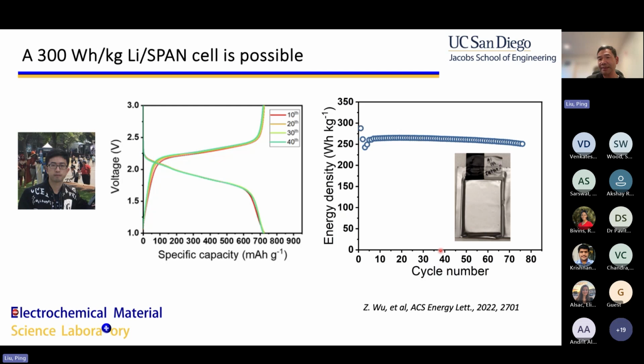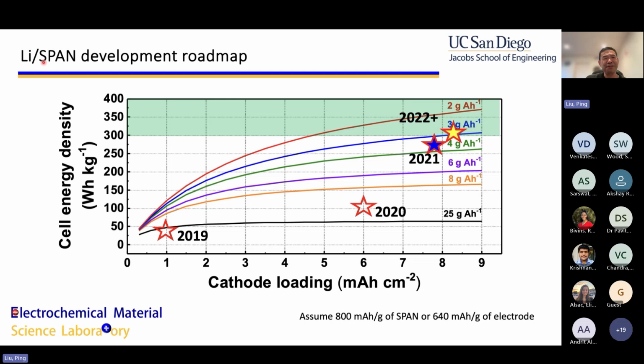It's a 2 amp hour cell, and this cell actually has a real energy density somewhere between 260 to 300 watt hours per kilogram, and it's not 500. But the cycling stability is very good. This work was done probably 4 or 5 years ago, and this performance remains one of the best in the literature even to this day. So we still continue to work on it. Now, you may ask, it's only 300, it's not 500. So what can we do to turn it into 500?